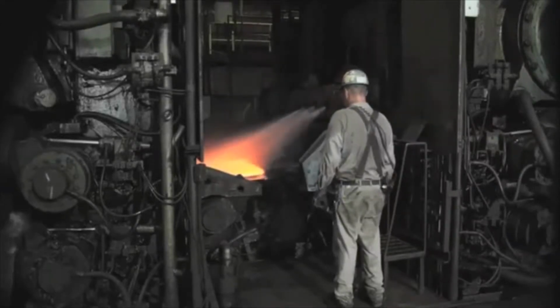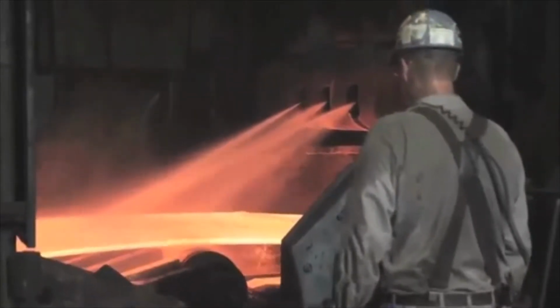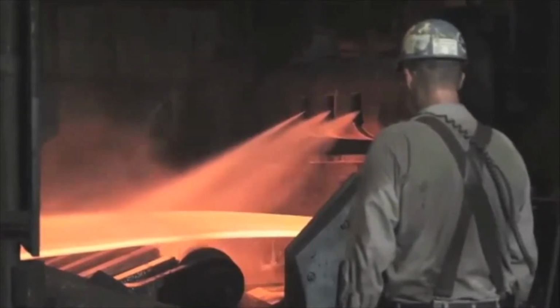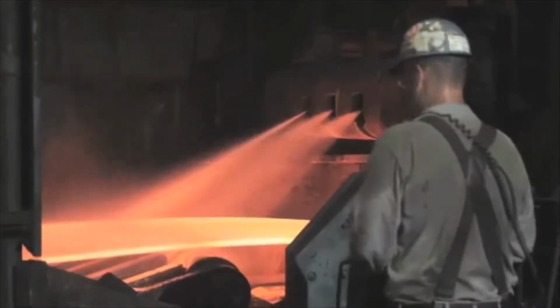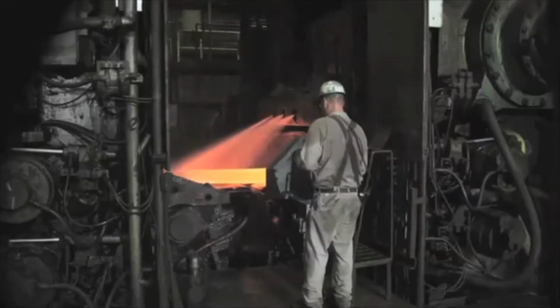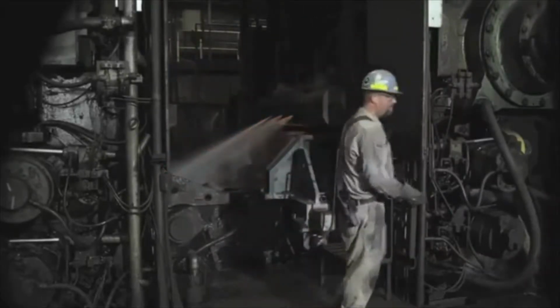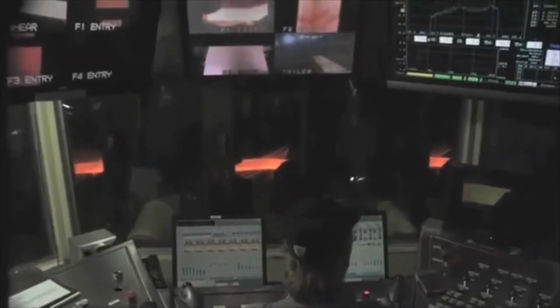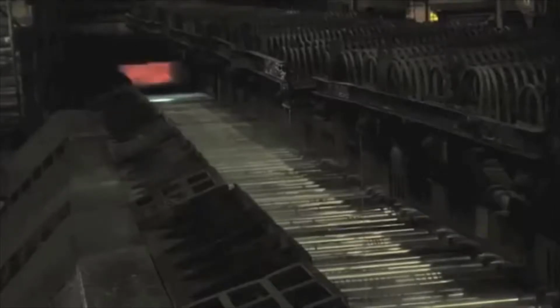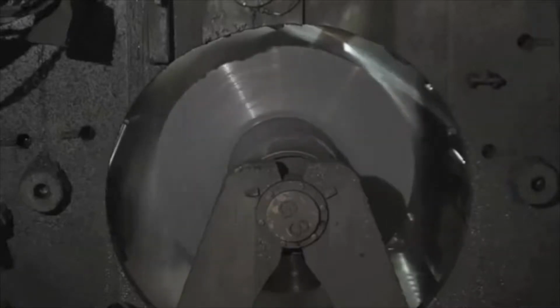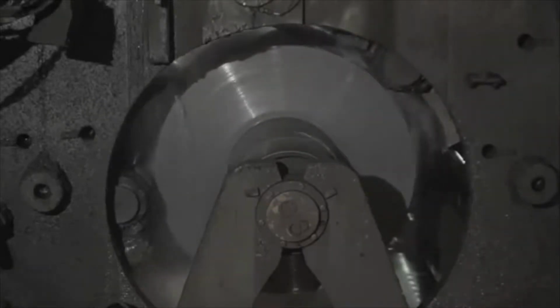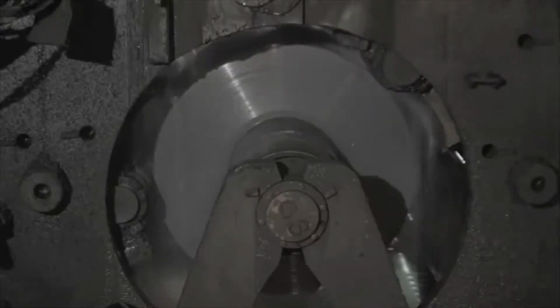Scale is removed from the slab before it's rolled, with water jets spraying 4,000 gallons per minute at 3,500 pounds per square inch. Slabs are reduced to meet customers' requirements on our 7-stand hot rolling mill. 7 10,000 horsepower motors drive the work rolls in the mill stands, and 4,000 tons of rolling force per mill stand reduces the thickness of the material to as little as 1 millimeter or 0.040 inches. A new hot band of steel is automatically coiled. On average, each coil weighs about 22 tons, or as much as 10 cars.